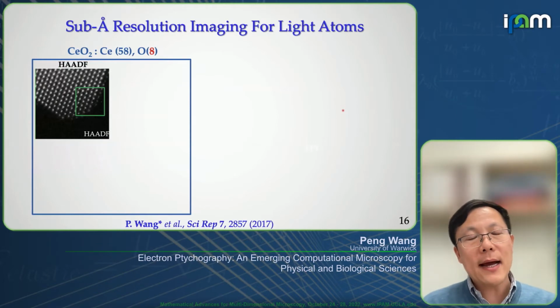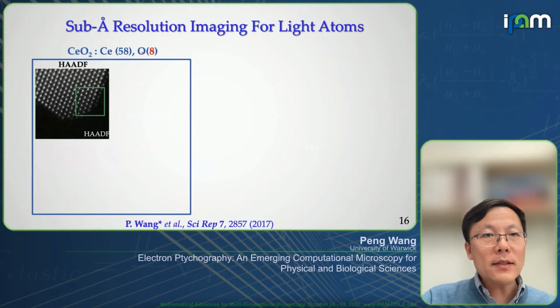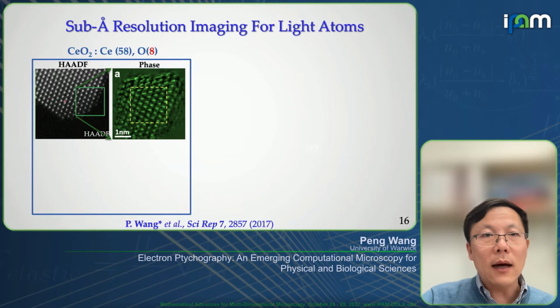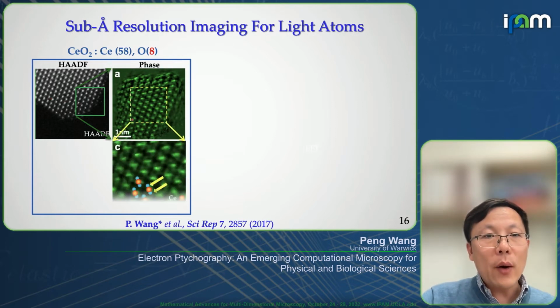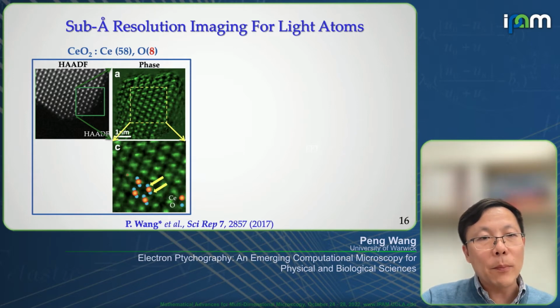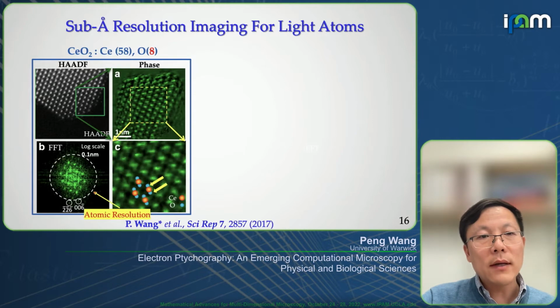And then we use cerium oxide as an example, a model system, because in cerium oxide, the catalyst particle, the atomic number of oxygen is 8, and cerium is 58. So oxygen is very light, and inside the cerium lattice, as you can see in the hard disk, you barely see the oxygen column, but in the phase, you are able to see a shoulder, that is, the oxygen column nearby the cerium atomic column. In terms of resolution, this is in the 1 angstrom range, and we are able to see spots. So this means you can achieve atomic resolution with high sensitivity using this phase imaging technique.